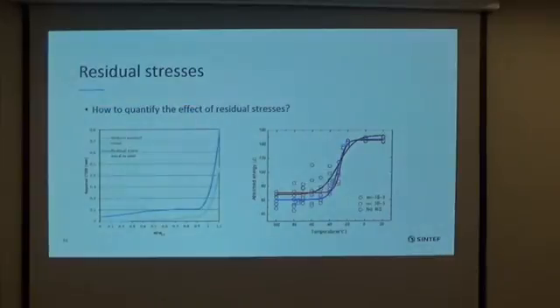And also the residual stresses after welding are an important issue. The question here is how to quantify the effect of residual stresses. We don't know. It's very hard to measure residual stresses, and very hard to really tell how much residual stresses can affect structural integrity. So in structural integrity assessment, we often assume a really conservative value. The residual stress can be up to yield stress, which is very conservative. How can we reduce the conservatism? And also how residual stress may affect the ductile to brittle transition. This will be a talk on Friday by one of our PhD students. You're welcome to join us.